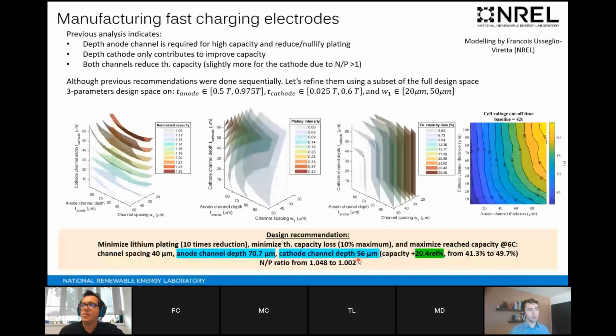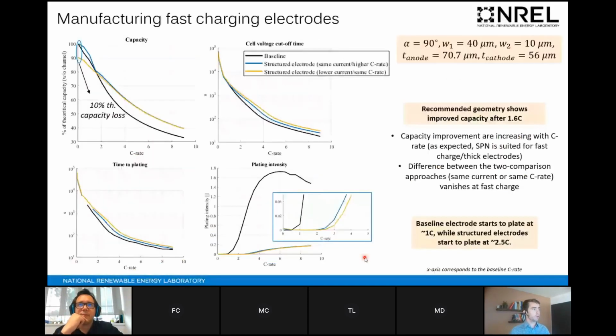So the two electrodes don't contribute equally to fast charging. The anode is the most important, and it needs the biggest improvement in transport. The cathode is not as much of an influence on the fast charging process, so it doesn't have to be laser ablated as much. And so Francois' models were predicting major benefits from introducing these features.